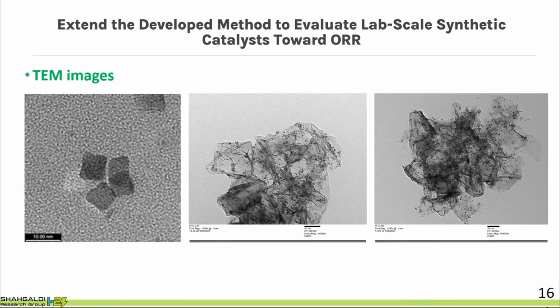So here in this image, you see that we applied a graphene sheet as a support for platinum, and we doubled the durability of our MEA by using graphene as a support for our platinum. So it means that the support plays an important role, and the shape of the catalyst plays an important role in terms of durability.